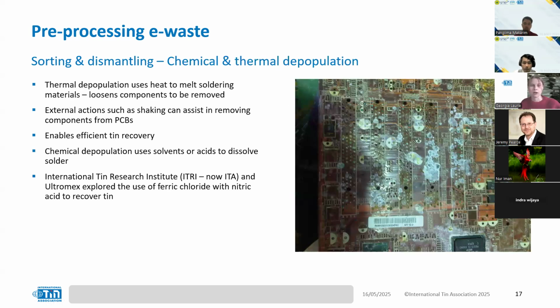So once PCBs are isolated and sorted from the bulk of material, there are many, many different processing routes that can be followed to recover tin amongst other metals. If we look at a direct route for tin specifically, we could use chemical or thermal depopulation, which directly removes the solder material. Thermal depopulation uses heat to melt the soldering material, along with some external force, such as shaking a board, for example, to help remove the PCB components while melting the solder.